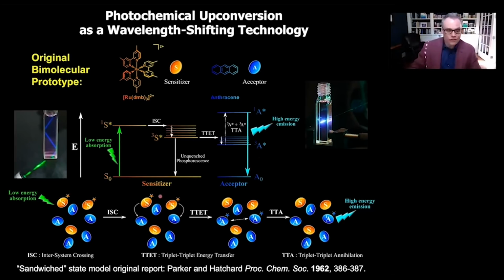Stoichiometrically, so everybody's on the same page, you have to basically make two triplet excited states in order to generate two triplet sensitized excited states in order to get one molecule that's going to give you higher energy emission or higher energy chemical transformations, as it will turn out. So the highest possible efficiency based on absorbed photons for this process is 50%. And there's a lot of details about quantum efficiencies of these processes.